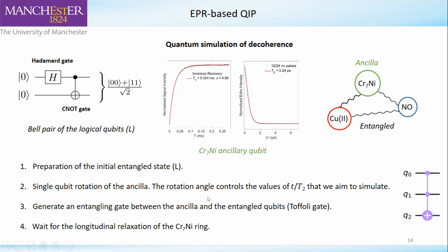And then if we generate an entangling gate between the ancilla and the entangled qubits using this Toffoli gate, and then just simply wait for the longitudinal relaxation of the chromium-7 nickel ring, we can read out how the chromium-7 nickel ring contributes to the decoherence of the entangled state of the copper and the nitroxide.